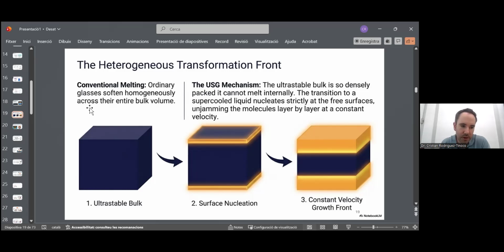So the same higher mobility that allowed us to prepare the ultrastable glass, because the mobility on the surface was higher, is now producing that the glass will start to transform back into the liquid state from the surface. Mainly from the surface, or also from the substrate, depending on the interaction between the glass and the substrate. If there is no very large interaction, we can also observe some transformation from the interface with the substrate. But in general, the transformation starts from the surface.